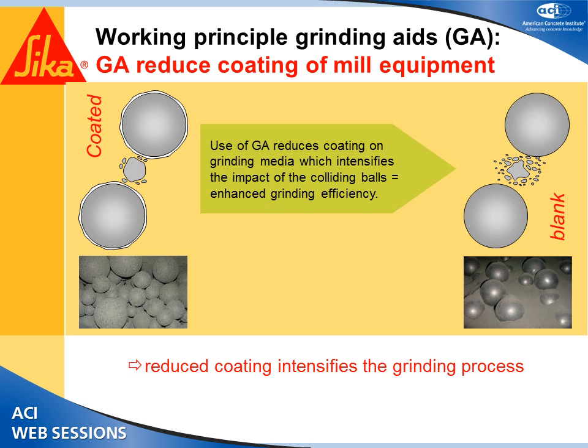The other thing grinding aids do is, because of these electrostatic charges, the cement tends to form a coating on the steel balls, and when that happens, it reduces the impact of the steel balls against each other and also against the clinker particles. So that reduces the efficiency of grinding. Whenever you're using grinding aids, because they repel the cement particles apart, you have less formation of coating on the steel balls, which increases the intensity of grinding, and you get faster production.